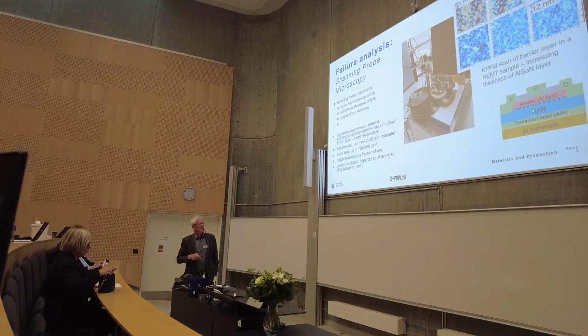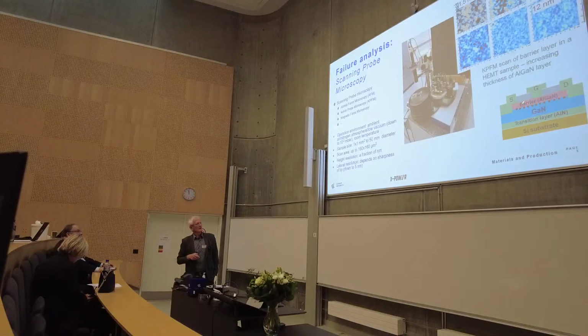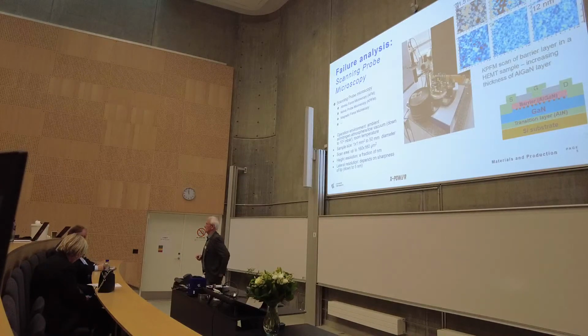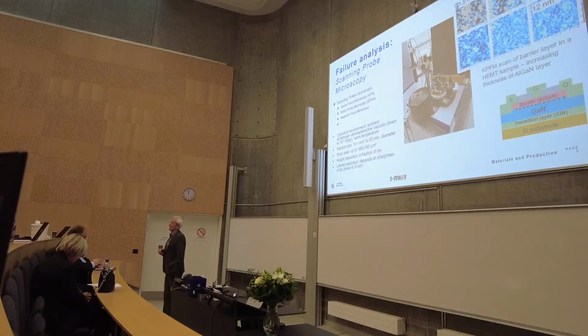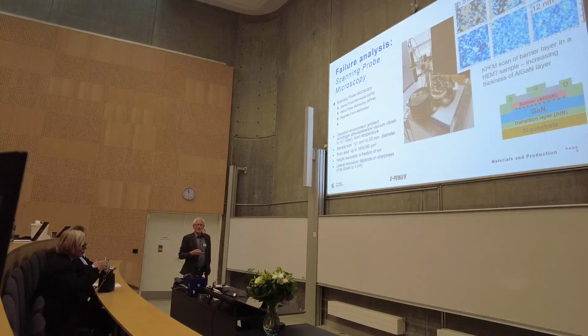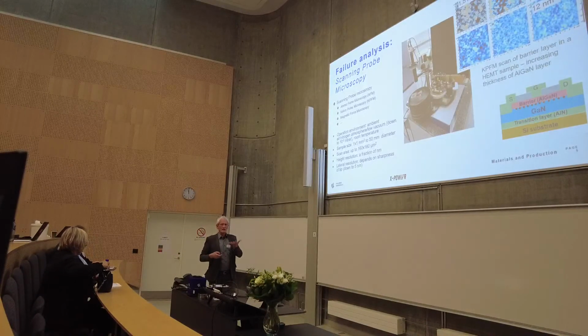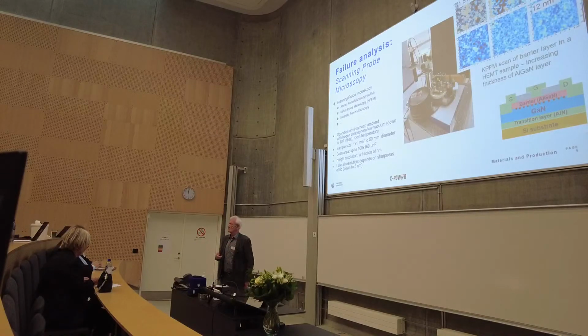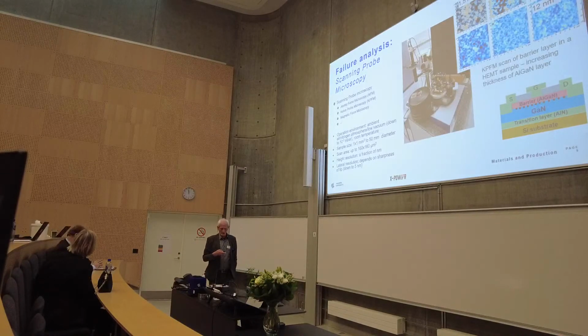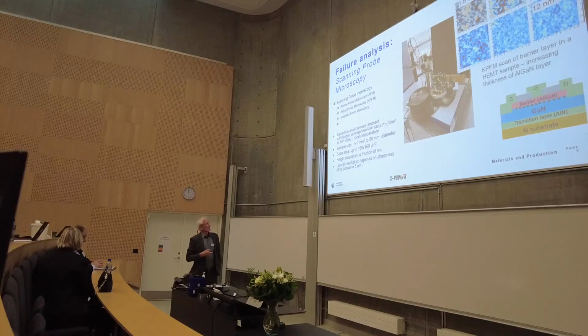This is an example of looking at a gallium nitride, aluminum gallium nitride wafer for a high electron mobility transistor. And how thin can the barrier layer on the top be? It's varied here from 1.5 nanometers up to 12 nanometers, and you can see from the electrical potential that it gets more and more homogeneous. So making the layer too thin simply doesn't work. You can test properties in addition to just the geometry of systems. You can start to look at electrical properties with the microscope.